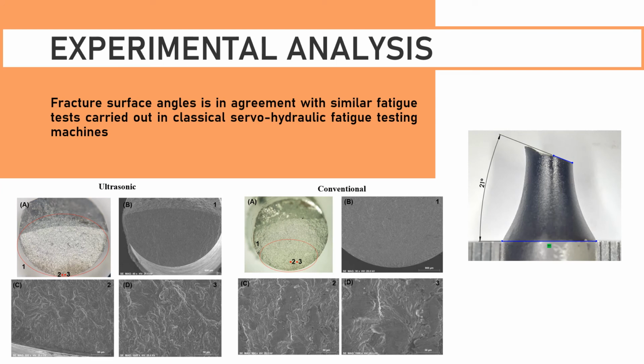So afterwards, we focused our work on comparing the angles and the fracture surfaces between specimens tested in conventional machines and tested in our ultrasonic fatigue machine. In this slide, we have a comparison between the uniaxial tension compression specimens, and we can observe various similarities between both specimens in the propagation and the initiation of the fatigue.